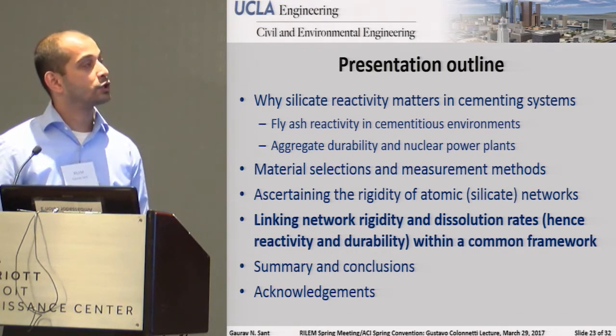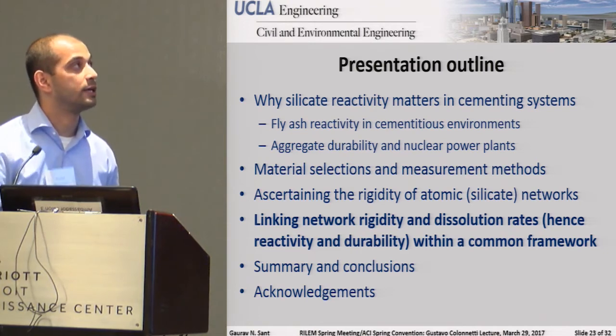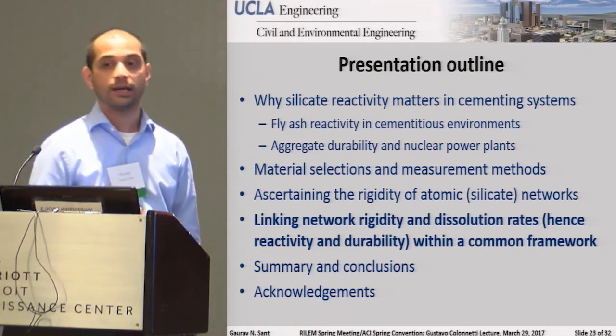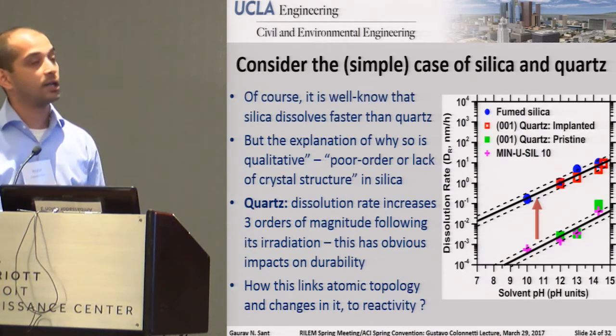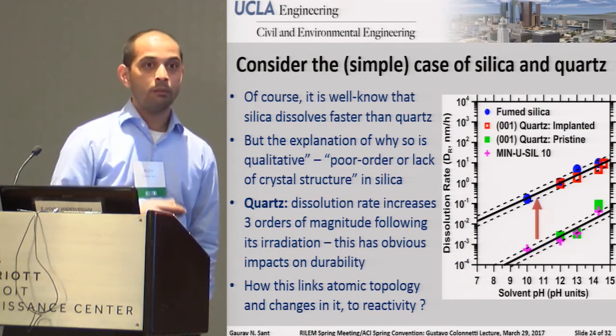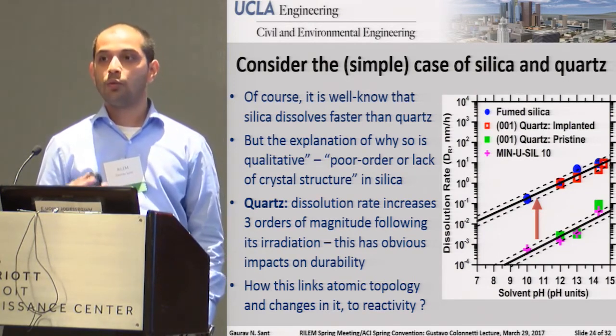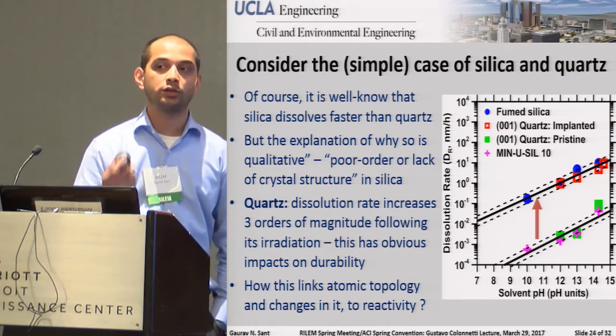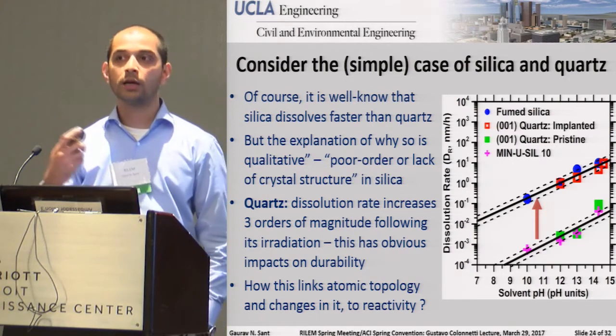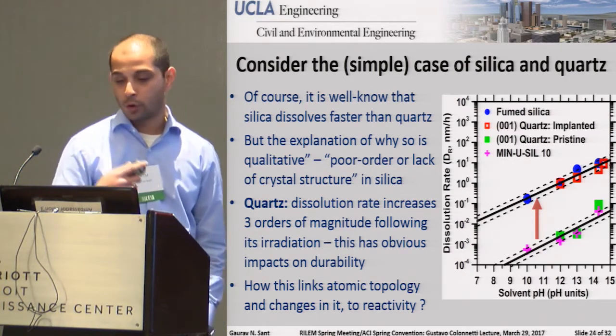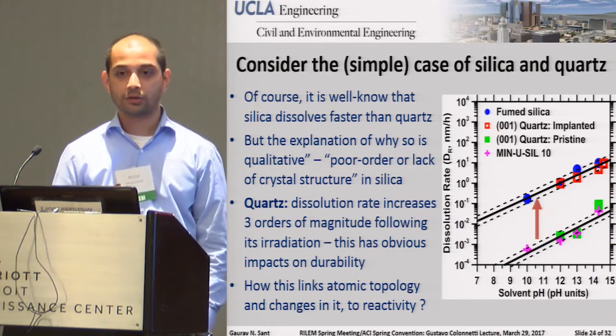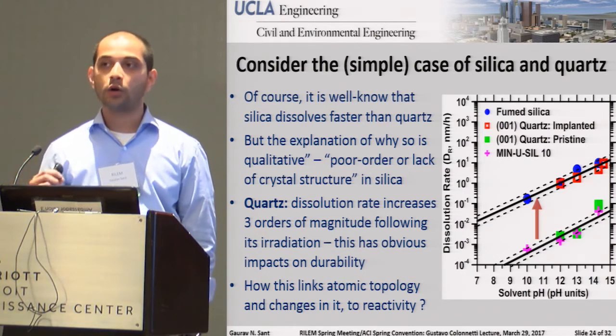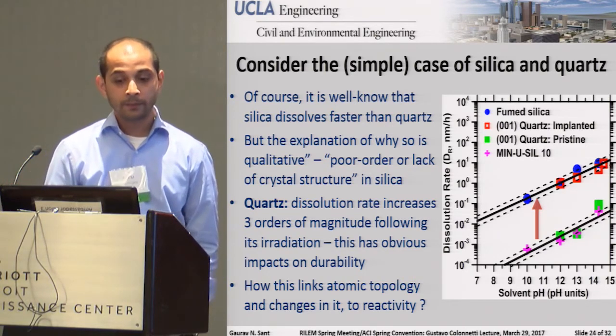So the first thing to start looking at, really, and I'll start with a simple case of silica and quartz, two classical silicate solids. It's well known that silica dissolves faster than quartz. But if you ask the question, well, why is that so? The answer that you get is always qualitative. The answer is silica's got poor order, right? Or it doesn't have a well-defined crystal structure. You don't really get any quantitative metrics that are associated with it.